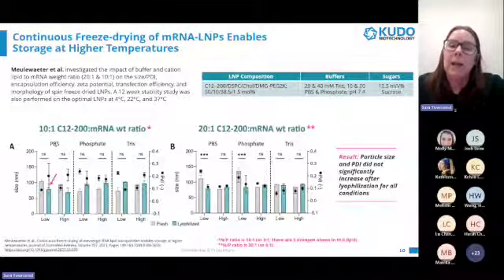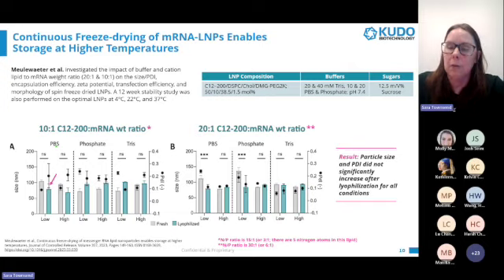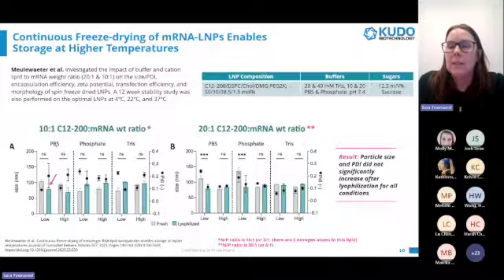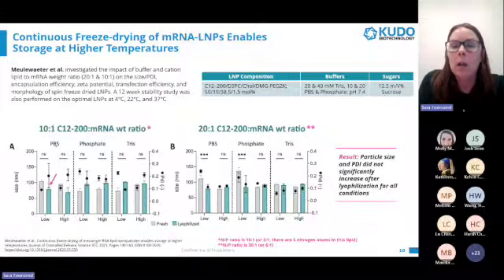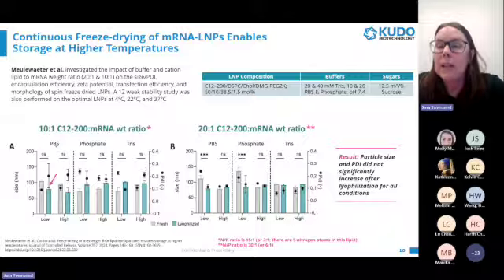This page displays the particle sizes for their three formulations at the two ratios. Note that for all formulations, the particle size and PDI did not significantly increase, and even decreased for some of their formulations after lyo. This is atypical and could be due to the particular lipid they used or their spin drying process.